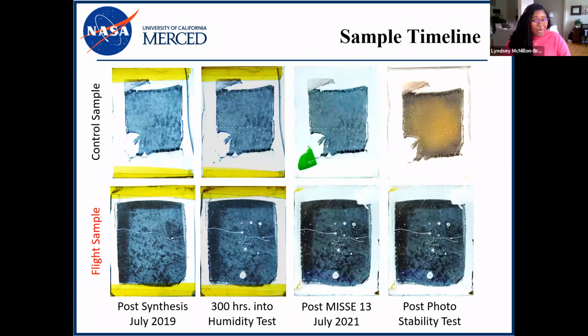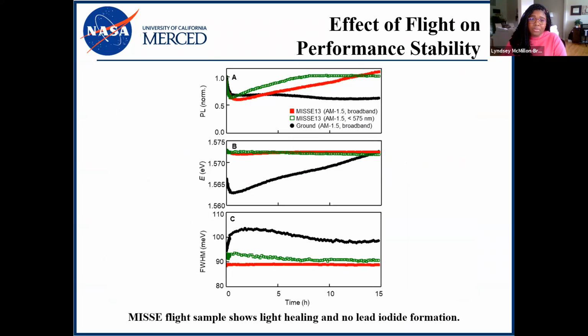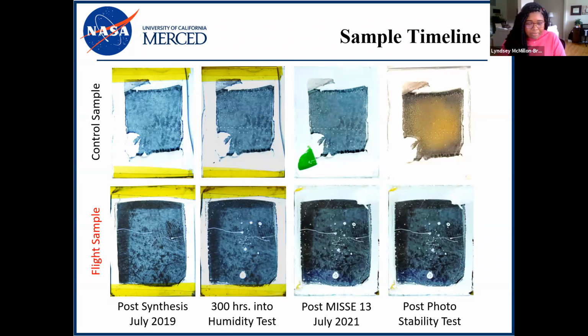So here are some photographs comparing the flight sample to the ground-based control after that light soak. Again, you can see that the control sample is showing that mustard yellow color. And after we let it rest for a bit longer in the lab, it went full yellow, so it's lead iodide right now. But the MISSE flight sample is holding strong, still the desirable black phase.